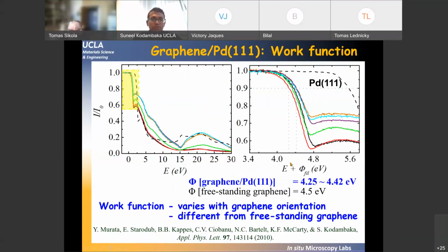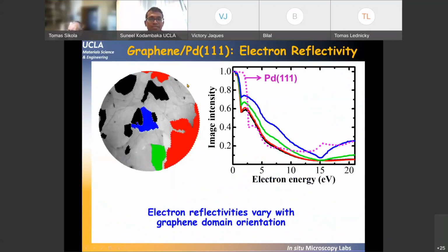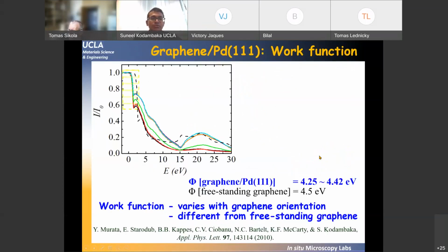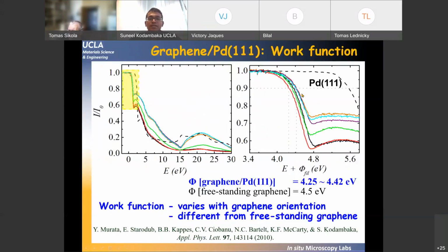Thank you. So here, first we collect the image intensity from a given field of view. Once you have the image intensities, then you choose the area of interest from which you want to measure the reflectivity curves. So if we want this from this red domain, let's say blue domain, then you maybe make a circle or a square and you collect intensities as a function of the electron energy. And then you get this blue curve, and you do the same thing for different areas and you get these curves.